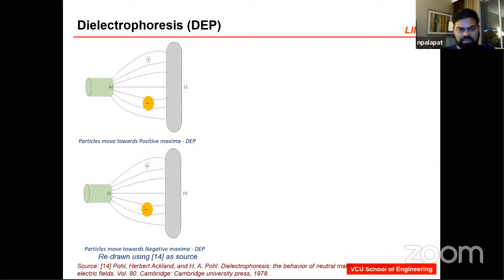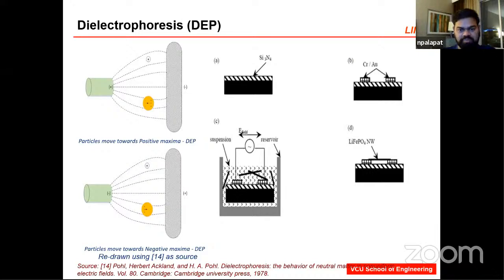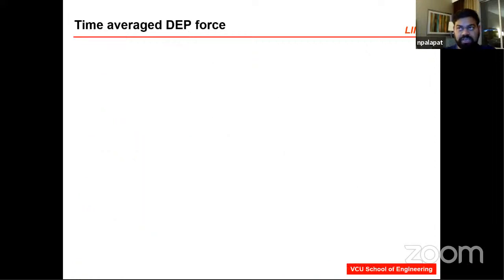So in my experimental technique, the chips that I have shown earlier, I've inserted the chip in an ethanol solution in which I put several nanowires, and I've applied bias between the biasing electrode and the unbiased electrode, thereby causing these nanowires to come and deposit exactly where I wanted. Here I'm showing a lithium iron phosphate nanowire that is deposited between the locations.